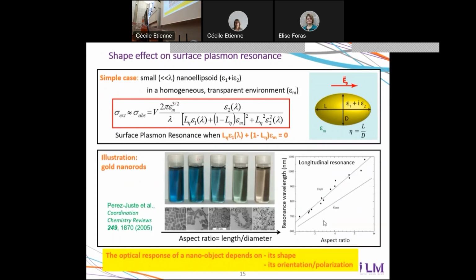Okay, and so all this was for spherical nanoparticles. So in this case, and small nanoparticles. In this case, the resonance condition is only set by the composition of the particle and of the environment. However, things are different for a nanoparticle with more complex shapes. For instance, for gold, for elongated nanoparticles, such as nanoellipsoids, the extinction cross-section becomes a bit more complicated with the appearance of shape-dependent factors, which also affect the resonance condition. So the result of this is that the resonance wavelengths and thus the color of solutions of elongated nanoparticles depend on how strongly elongated they are, depend on the ratio between their long and short axis.